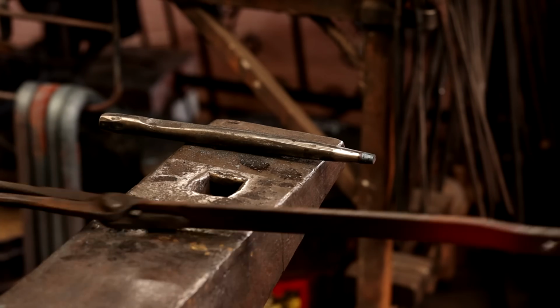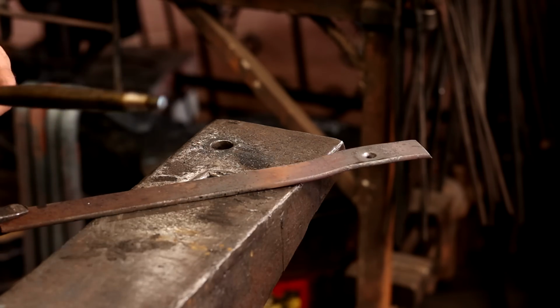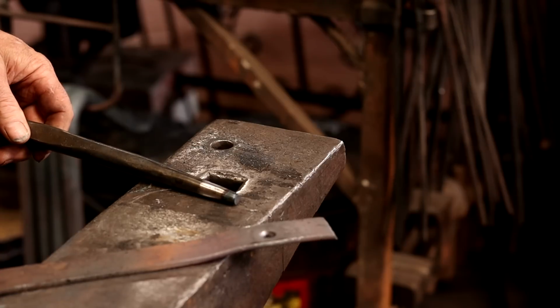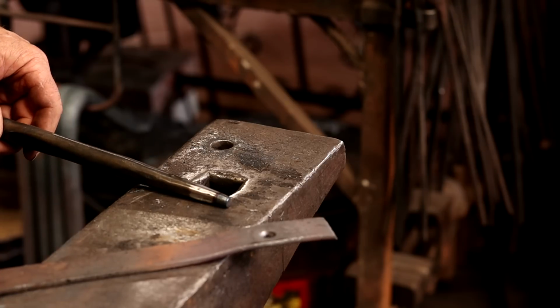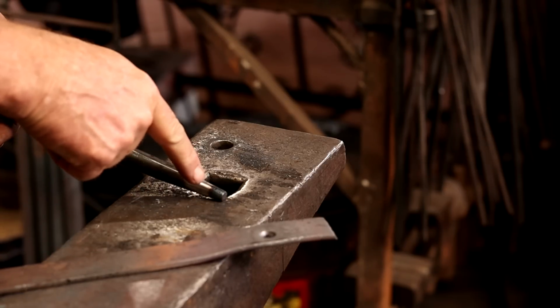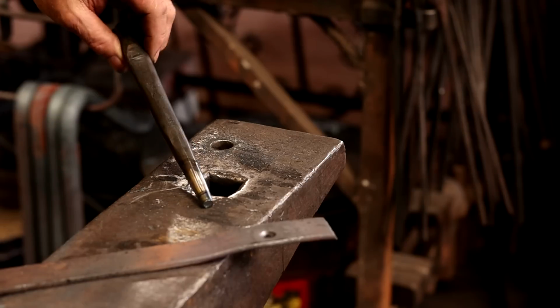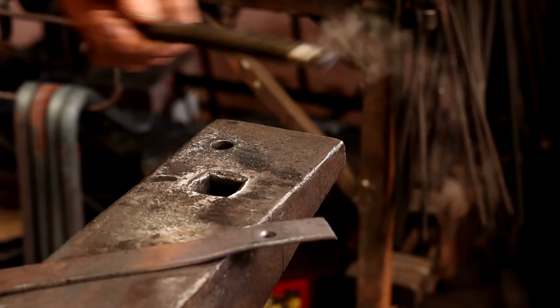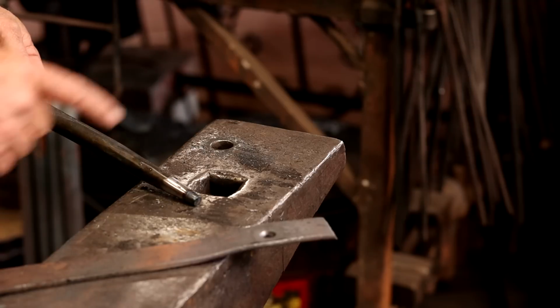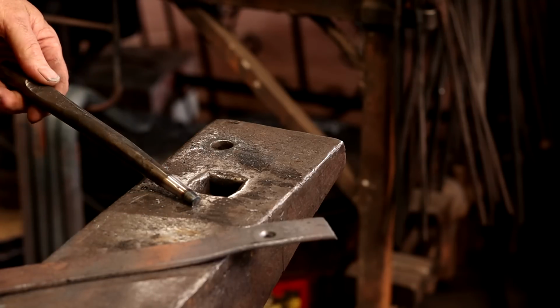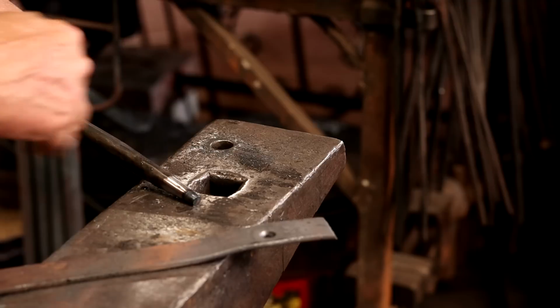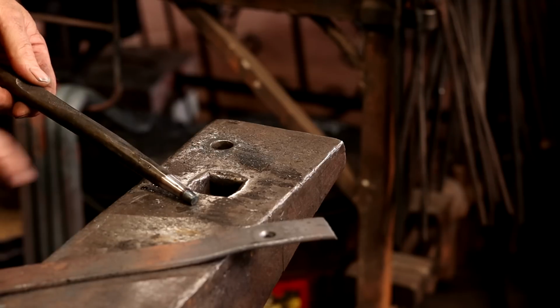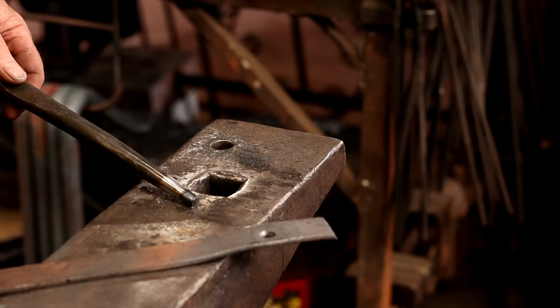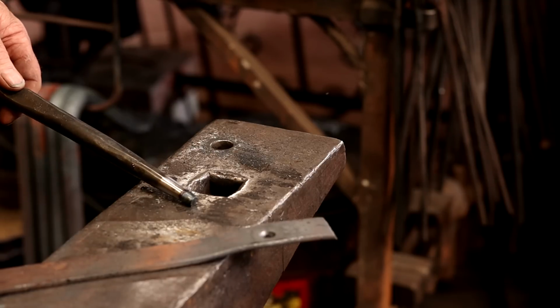So we can definitely punch a hole. Now we can see that this is already tempered up into a blue range as a result of being in contact with the heat. And that's probably not going to hurt anything in the long run, but the hotter that gets, the softer it's going to get and the more temper you're going to draw in it. So try not to let it get too hot. This is probably considerably softer now, but still way harder than hot steel.